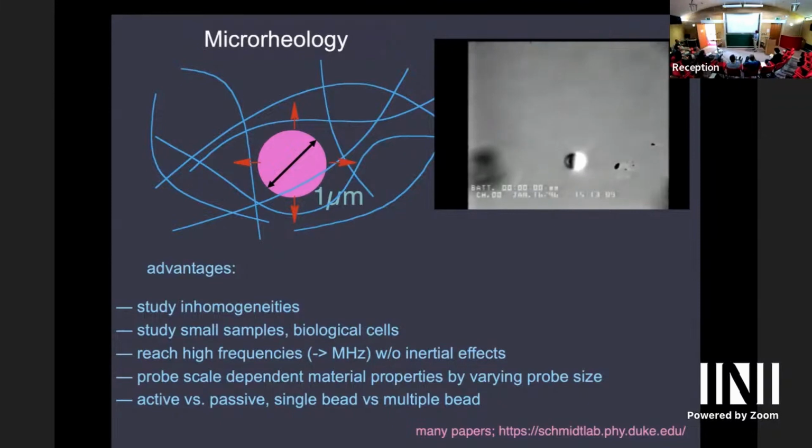This is a video. So either use thermal fluctuations. So now you see that, well, now it's what we call active microrheology. Now there's an optical trap pulling on this thing, but in between, passive Brownian motion. The gel is fairly soft. You don't see the actin here. It's 1 mg per ml, 1 milligram per milliliter filamentous actin. So it's entangled, not really cross-linked. And that bead is doing Brownian motion just driven by thermal excitations. And you can use that to deduce the shear elastic moduli of the environment.